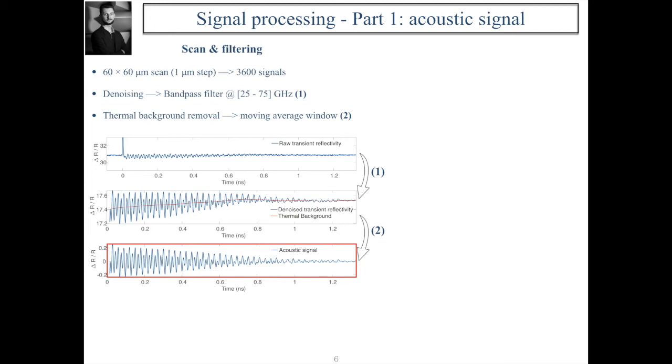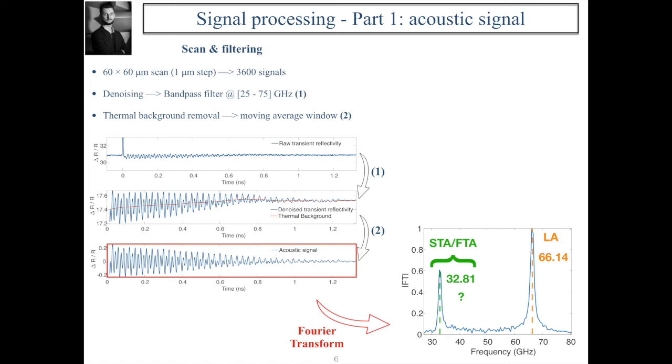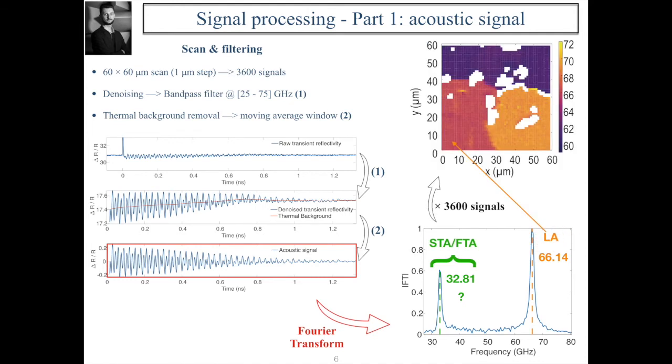the signal. Applying a Fourier transform to the full acoustic signal gives information on which acoustic modes have been monitored or not. In the best possible cases, each of the 3 acoustic modes is monitored. This Fourier transform allows us to extract the frequency of the Brillouin oscillation of each acoustic mode. And finally, if we regroup on the same representation all the contributions of the signals for a common mode, we can recreate a map of the Brillouin oscillation frequency depending on the position of the scan for one mode, here